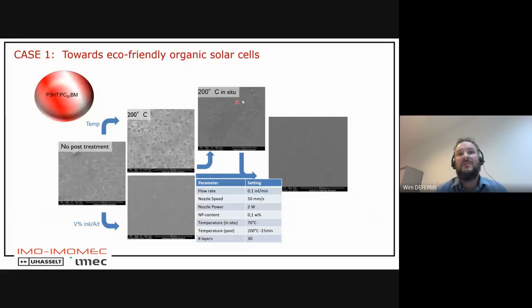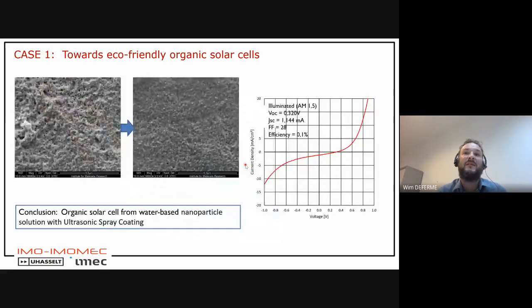And to get this closed layer, we needed an in-situ treatment of around, let's say, 200 degrees centigrade to more or less melt these nanoparticles and have a flow, a homogeneous covering of the layer. And this is of course influencing the final properties, because if we finally look at our final layer in an organic photovoltaic device, the efficiency we reached with ultrasonic spray coating was only 0.1%.